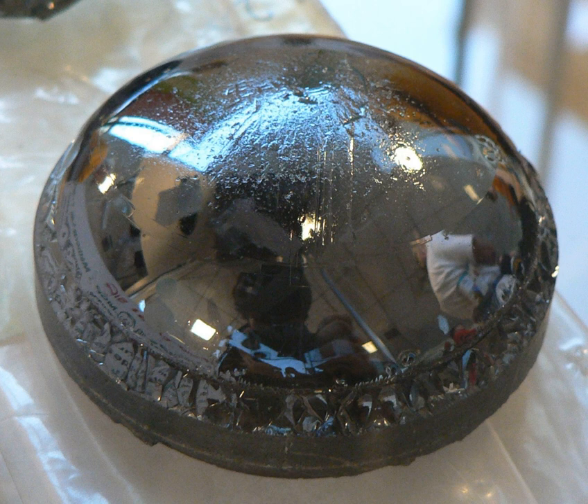Steel production. Silicon carbide, dissolved in a basic oxygen furnace used for making steel, acts as a fuel. The additional energy liberated allows the furnace to process more scrap with the same charge of hot metal. It can also be used to raise tap temperatures and adjust the carbon and silicon content. Silicon carbide is cheaper than a combination of ferrosilicon and carbon, produces cleaner steel and lower emissions due to low levels of trace elements, has a low gas content, and does not lower the temperature of steel.